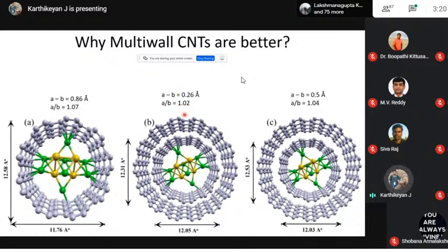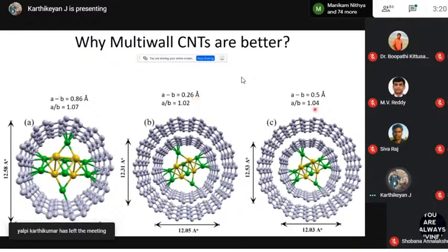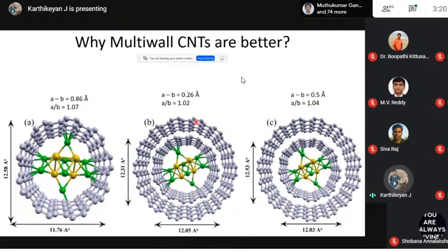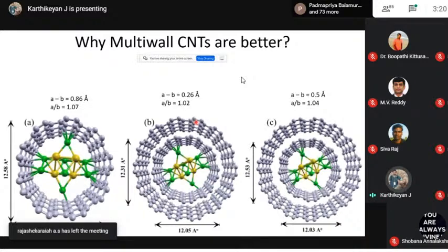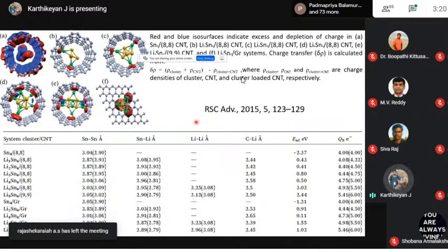But if you go to multi-wall CNTs, we measured the A by B ratio for the inner CNT. For the inner wall of the multi-wall carbon nanotube, the difference between A and B is only 0.26 Angstrom. This clearly shows that when you use multi-wall carbon nanotubes, mechanical stability is really achieved. We can control the expansion of these tin-lithium alloys during the charging process by using this multi-wall CNT and tin nanocomposite. So what is really happening, how is it interacting with the CNT?